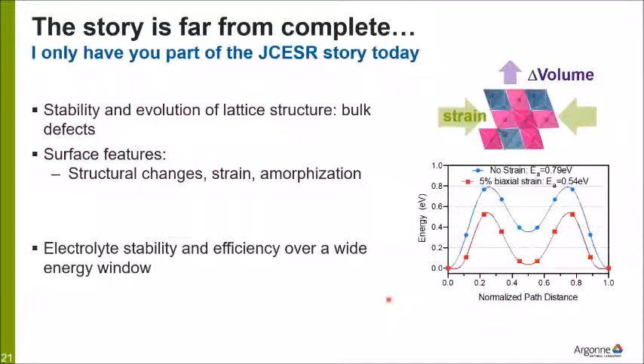I've only told you part of the JCESR story today. A better understanding of the stability and evolution of the lattice structure, for example, the anti-site defects or inversion, is key. Additionally, surface features are very critical, and we can see that. I didn't go into detail, but between nanoparticles and submicron particles, we can see very dramatic differences that don't seem to be related to the magnesium bulk diffusion. The structural changes at the surface, strain, amorphization, over-magnesiation. And so here's just an example of some computed energy barriers, no strain, and then biaxial strain that you might find in a thin film that would isolate surface effects.